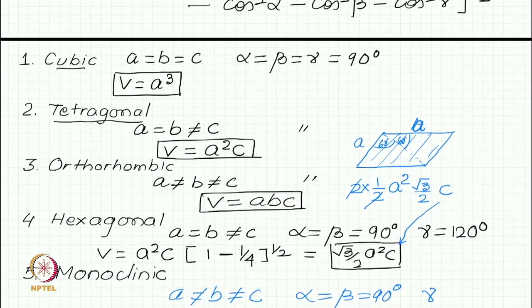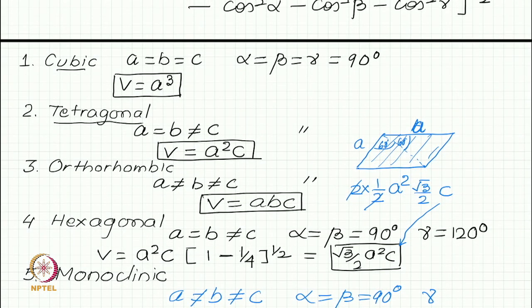It is central to all science in a way. Symmetry is very important, but we will look at it from a more restricted perspective of crystallography, and in particular we will see that these crystal systems are defined in terms of symmetry and not in terms of these lattice parameter relations. So, for example, in hexagonal crystal you can very easily find an orthorhombic C unit cell, that does not make it orthorhombic C, or in cubic crystal you can very easily find a rhombohedral or trigonal unit cell, that does not make it rhombohedral or trigonal.